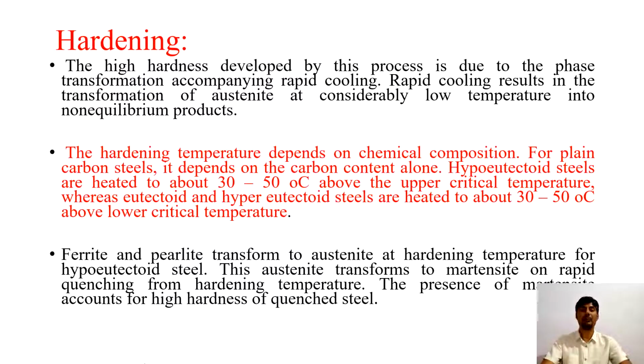The hardness developed by this process is due to phase transformation accompanying rapid cooling. Rapid cooling results in the transformation of austenite at considerably low temperature into non-equilibrium products. The stable structure does not occur during hardening process. If we are doing rapid cooling of our material after heating, then we are getting austenite directly to martensite structure. There is no time to change this transformation to pearlite and bainite. So there is no stability of these structures in our product while we are doing hardening at a rapid rate.